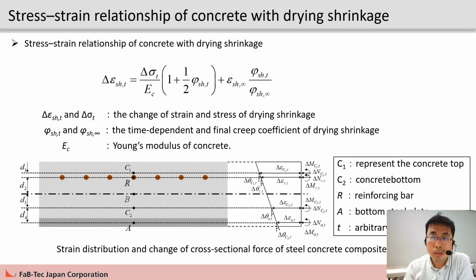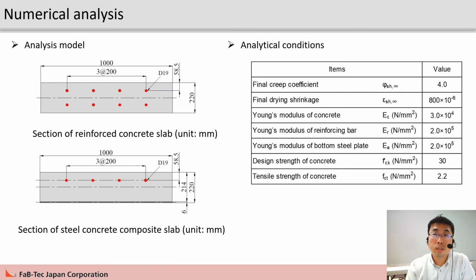Based on the analytical results, a stress-strain relationship for drying shrinkage of concrete is derived as follows. This figure shows the strain distribution and amount of sectional cross-section force change of steel concrete composite slab. This figure shows the section of the reinforced concrete slab and steel concrete composite slab respectively. A comparison of the change of stress in a given cross-section due to drying shrinkage must include the degree of restraint. The analysis models include specimen types 2 to 4 and the investigated conditions are listed in this table.